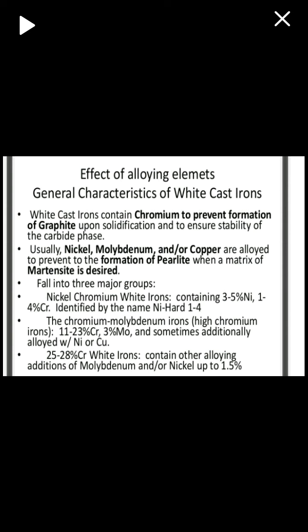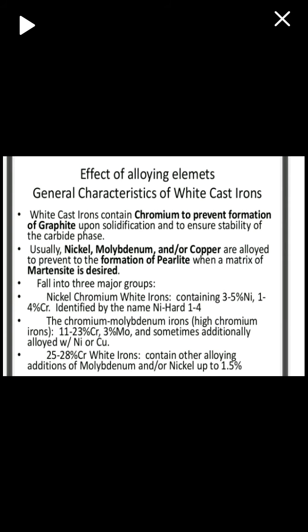First, nickel chromium white cast iron containing 3 to 5% nickel, 1 to 4% chromium, identified by the name of Ni-Hard 1 to 4. Second, the chromium molybdenum irons, high chromium irons, 11 to 23% chromium, 3% molybdenum, and sometimes additionally alloyed with nickel or copper. Third, 25 to 28% chromium white cast iron contains other alloying additions of molybdenum and nickel up to 1.5%.